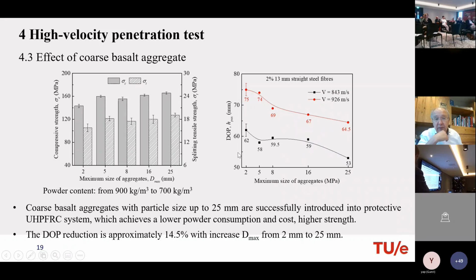And here we can see also the depth of penetration, which actually is lower with bigger aggregate size. So the strength statically is almost the same, but dynamically with the bullet, with 2 speeds, you can see the speeds here and also the depth of penetration. You can also see the effect of a speed increase from 840 to a little bit more than 900 meters per second. There you have already quite a big increase in penetration depth. But you can also see here that with increasing aggregate size, the depth of penetration is reduced. So very nice result.